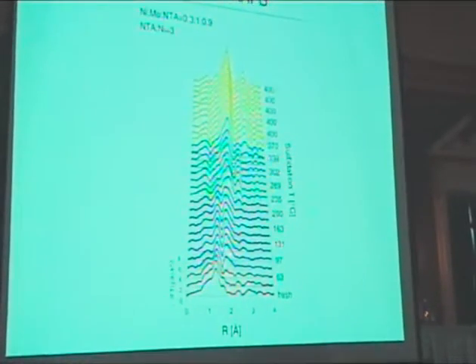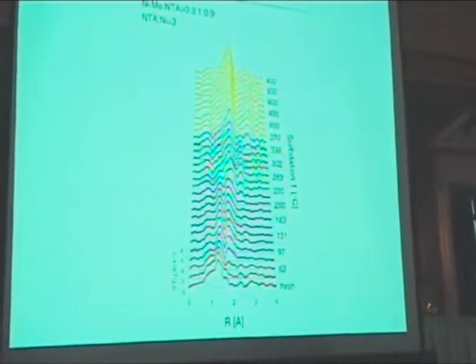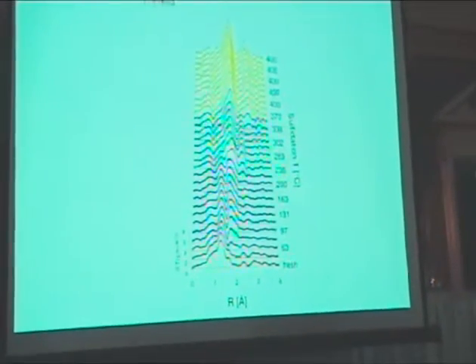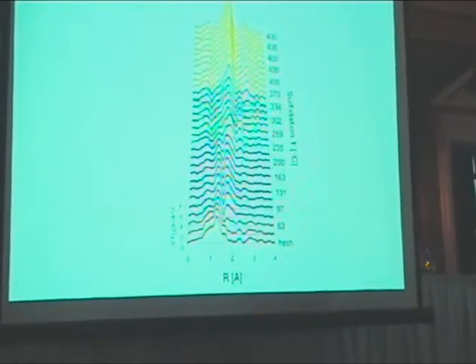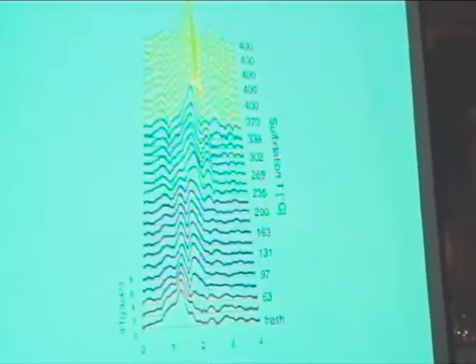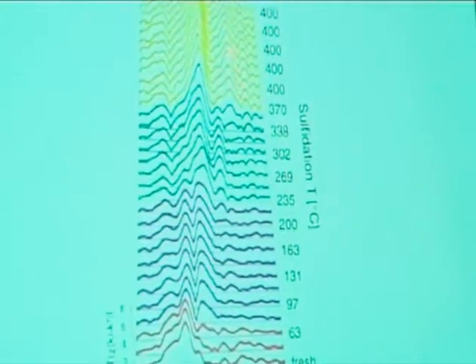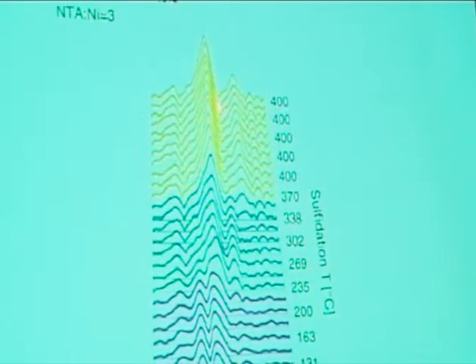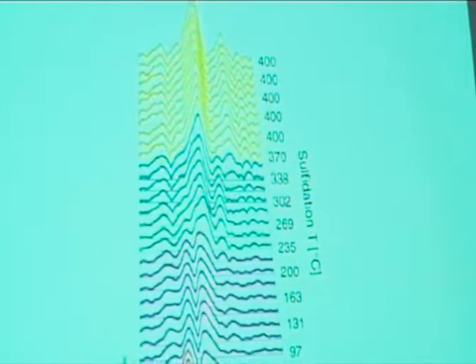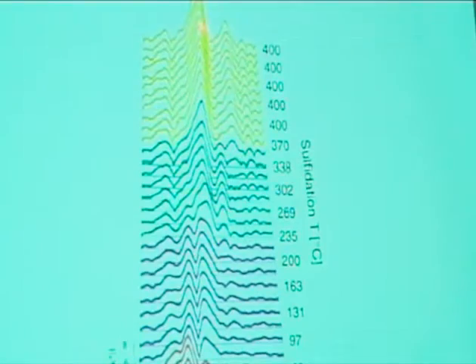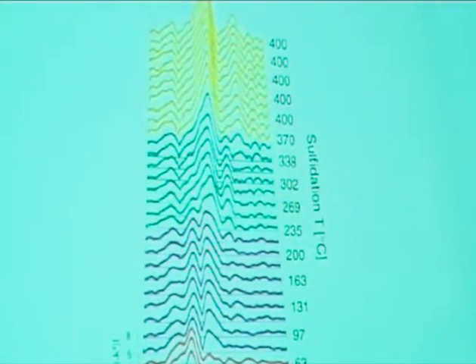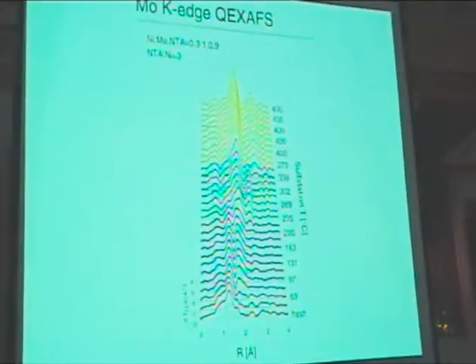Then we increase the temperature, we are still flowing H2S, and you see a new peak come up, and the shoulder is going. Here is a new peak growing in, which I've colored with a new color. Then another new peak is coming up here as well, and this peak is disappearing. In the end, there is another new peak, even more to the right, which is also a little bit shifted, though you cannot see it so well in this presentation. And in the end, it looks like a 2-peak spectrum, and that is exactly what you expect for MoS2.